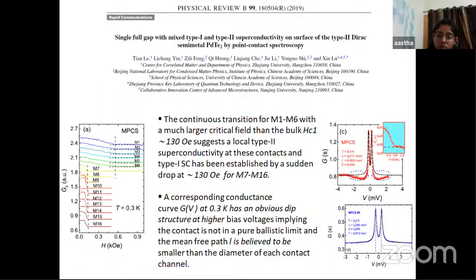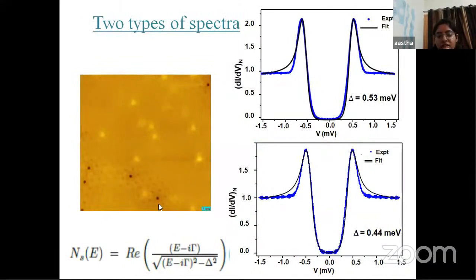So what we can do is artificially disorder the system to look at what happens to this inhomogeneity in the mean free path. We did such experiments by intercalating copper between the PdTe2 layers, and what we observed is that the system becomes homogeneously type 2 and this mixed phase disappears. We investigated that phase. This is the STM image that we got for copper intercalated PdTe2. Here the copper intercalation is 4%.